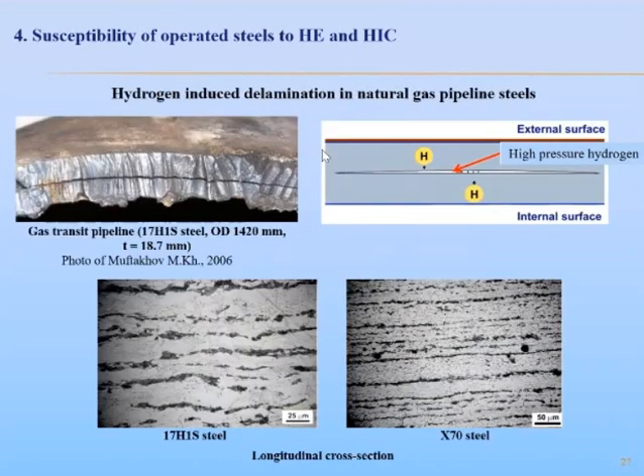Rolled steels are commonly susceptible to delamination cracking, since they are characterized by a banded microstructure, and non-metallic inclusions are also elongated in the rolling direction. Here you can see typical microstructures of rolled pipeline steels. Generally, the lamination is formed by a plane with relatively weaker texture parallel to the rolling plane within the steel due to any aspect that leads to anisotropic microstructure, including plastic deformation and so on. Damaging also accumulates in the rolling direction during long operation, facilitating cracking along the pipe axis.